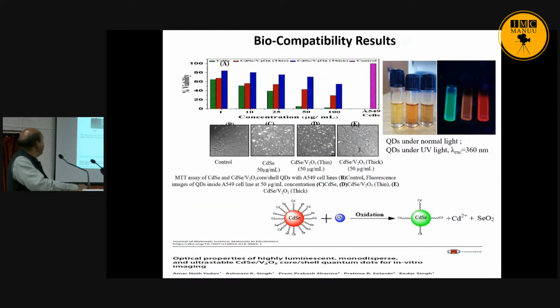And another application, very simple, is biocompatibility. If you see, Cd is a heavy metal, so CdSe is toxic. But if you want to know about the toxicity of the CdSe/V2O5 core-shell, we take some cells. Then with the help of these cells, we check biocompatibility. The biocompatibility of CdSe/V2O5 is higher than CdSe. At higher concentration, CdSe biocompatibility is only 5%, while CdSe/V2O5 is about 50%. It means the core-shell quantum dot is more biocompatible compared to CdSe.